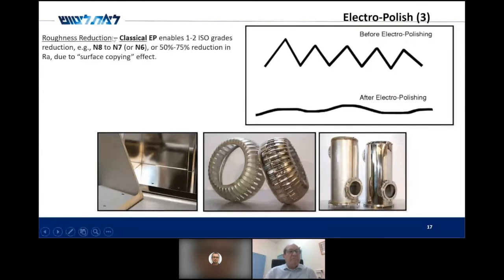So roughness reduction in classical electro-polish, which I'm discussing today, enables between 1 to 2 ISO grades, like from N8 to N7 or from N8 to N6, which is equivalent to between 50% to 75% reduction in Ra, in microns or micro inches, due to some surface copying effect. And this is what can be achieved with classical electro-polish.